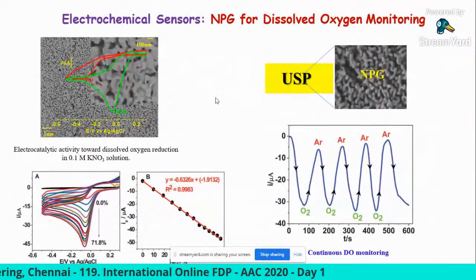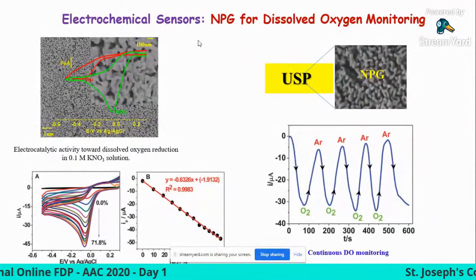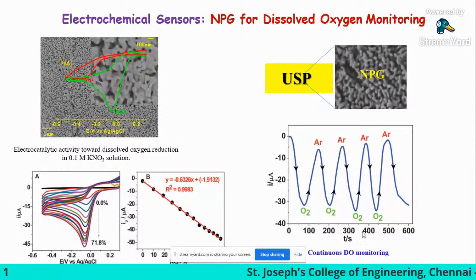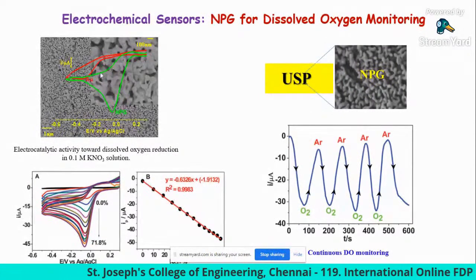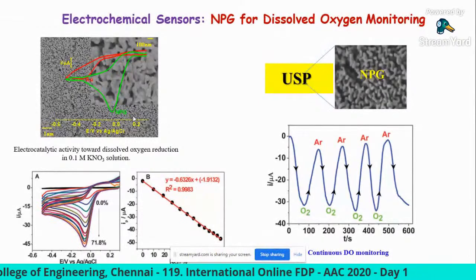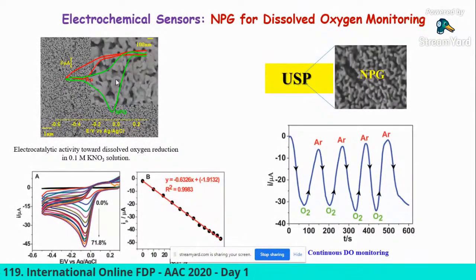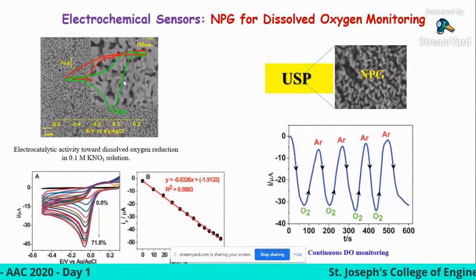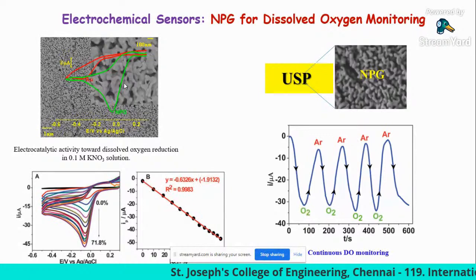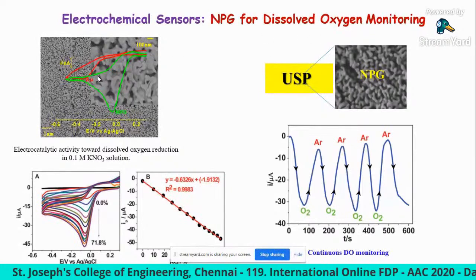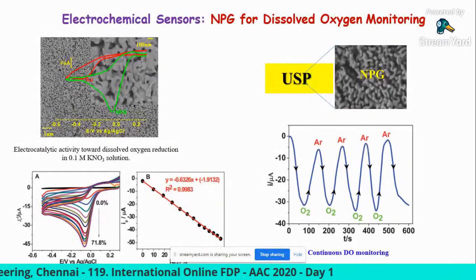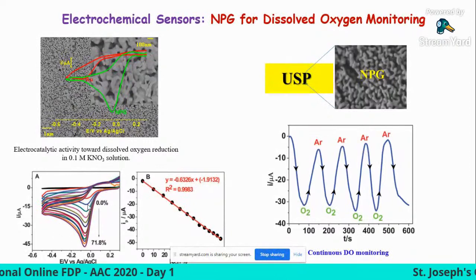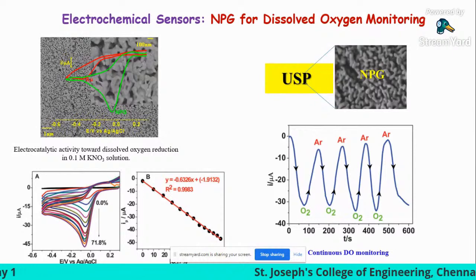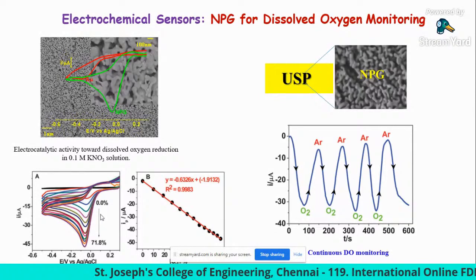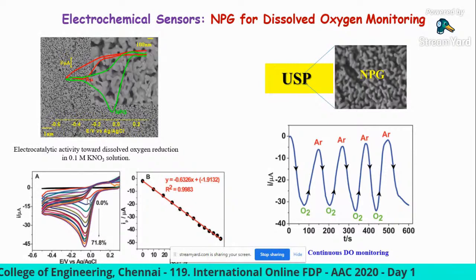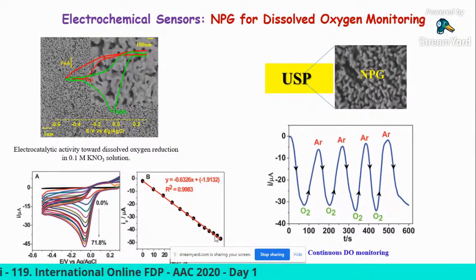Then, after the fabrication process, we have used this material for continuous monitoring of the dissolved oxygen. This is what I explained in the previous slides. This is the cyclic voltammetric responses of bare gold and nanoporous gold for oxygen reduction reaction, where the fabricated material shows excellent electrocatalytic activity for oxygen reduction reaction, and this is the cyclic voltammetric responses of oxygen recorded at different concentrations from 0% to 71.8%, where you can see the current is linearly increased with respect to concentration.